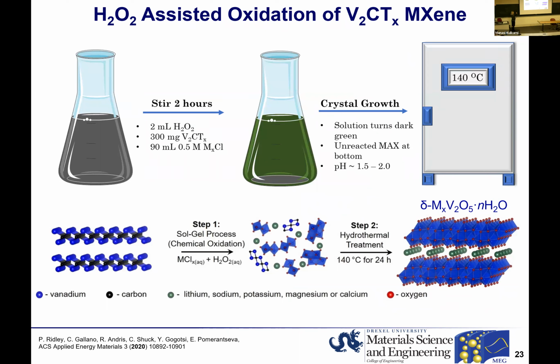So what we've done, the synthesis is just the same. Again, we use hydrogen peroxide in the presence of metal chlorides, but the reaction actually occurs much faster than in the case of the alpha V2O5 precursor. And here we use vanadium carbide, V2C, as a precursor. And what's also interesting is that this is not the actual photograph, but the color of the solution in the case of the synthesis with MXenes is green. So it's already different compared to the alpha V2O5 synthesis.